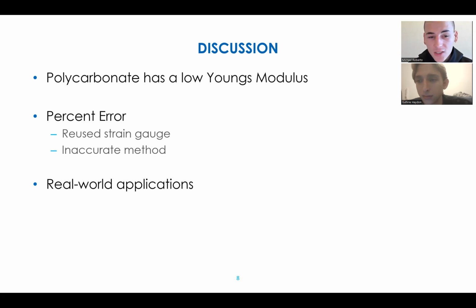And then our percent error, the reasoning behind the percent error is mainly because when we first were setting up our experiment, the strain gauge was broken and the soldering came off. So we had to use a strain gauge that was already used in the previous lab. This means that the properties of the polycarbonate were changed a little bit due to the force being placed on it in the previous lab, as it already went through 3-point bend. And this would have changed the values taken from the voltage and the displacement, which would then affect our equations.